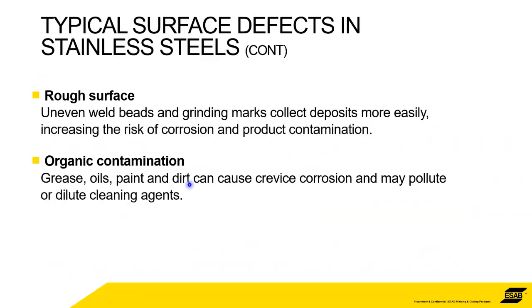Surface, I've mentioned this before, so uneven weld beads, grinding marks, these collect deposits, these accumulate rubbish, dirt, whatever, dust, and so it obviously increases the risk of corrosion, and you get product contamination. And then organic contamination, such as oils, greases, if you've got some machining oils, greases from assembly, paint as well. These can cause crevice corrosion, so it can hold moisture underneath the surface, and you get an actual crevice corrosion decay.